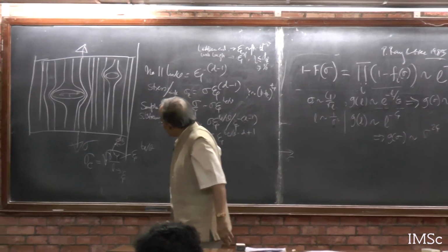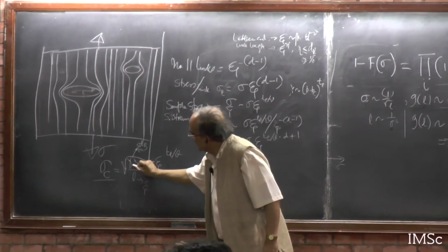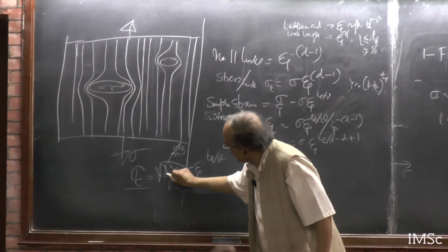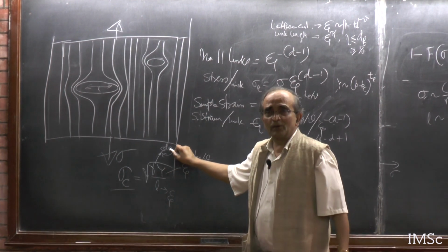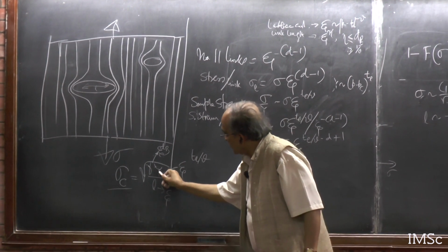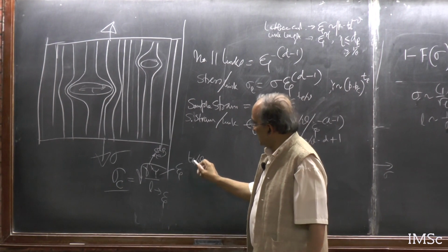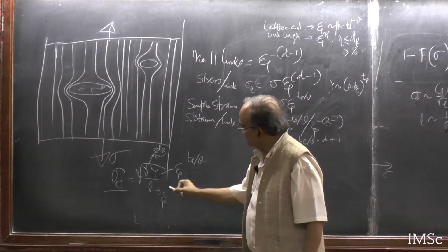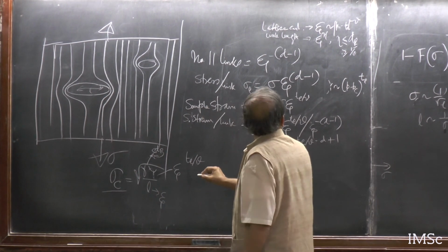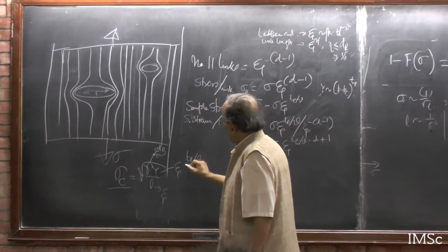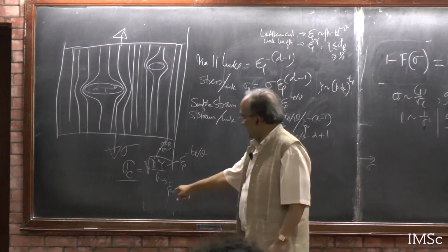In a sense, this calculation will tell you the Griffith calculation, with the surface energy density going as xi to the power backbone dimension, modulus of elasticity going as p minus pc to the power Te, and that means xi to the power this, and maybe this is minus, and then this length goes as correlation length.